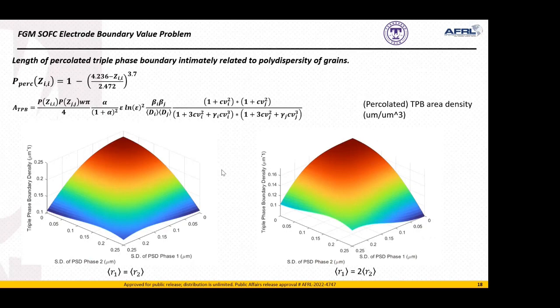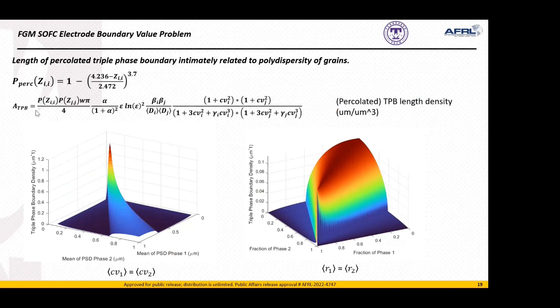Adding our percolation theory here, we arrive at this equation here, which defines locally the area of the triple phase boundary. And you can see here that the triple phase boundary density increases if the particle sizes are monodisperse. So the more we shrink down the standard deviation of the particle sizes, the more evenly distributed those particle sizes are, the better triple phase boundary we get, the higher density we get. Here you see on the right-hand side a diagram where the average particle diameter or particle radius of phase one is twice that of phase two, and so you get this shifting in the map.